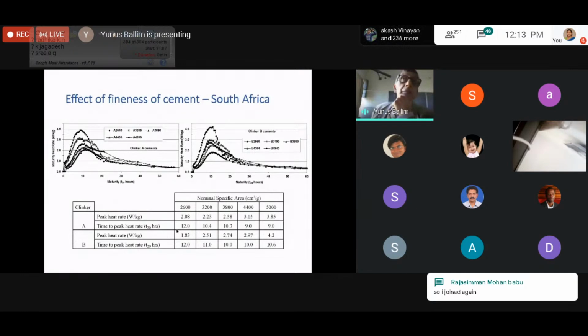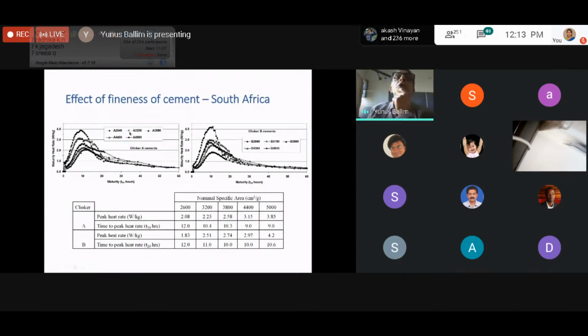Fineness of grinding is very important. Here we took 2 cements, clinker A and clinker B, and we changed the fineness from below 2600 square centimeters per gram to almost 5,000 square centimeters per gram, and you can see how the heat rate function changes. More importantly, not only does the peak heat rate increase, the peak also occurs a little earlier. And you see that with both of these cements.